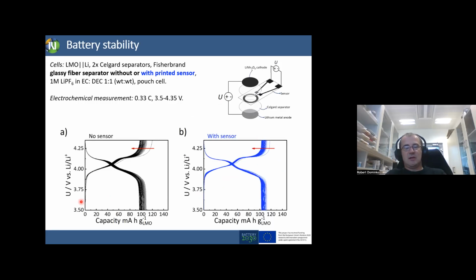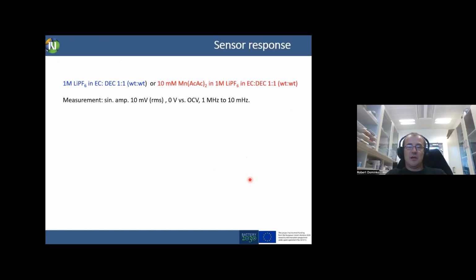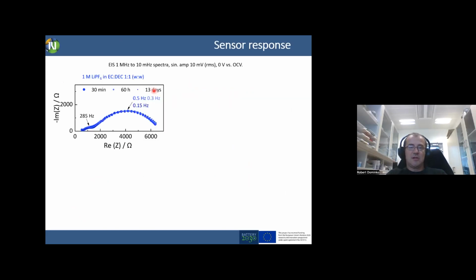So next, what we did, we cycled the cell with the sensor and without the sensor, but of course, in this case, without the sensing layer. So we don't see huge differences. I think the differences are within the experimental error a student can make. And then we moved back to the electrolyte that contains dissolved manganese cations. In our case, we put a 10 millimolar concentration of manganese acetylacetonate inside the electrolyte.